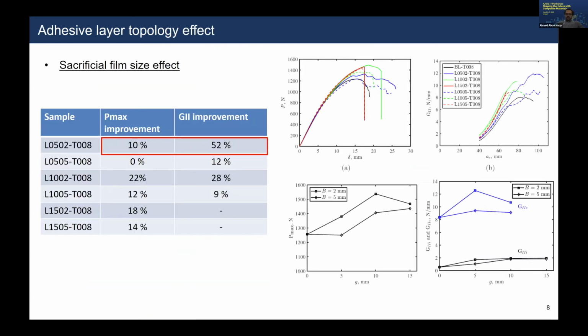For the topology effect, we study different P and G values for this bio-inspired adhesive joint. We reach the conclusion that the smallest crack width and the smallest G achieve a good improvement in fracture toughness and maximum load as well. The maximum load differs with the change of P and G, but finally we get a conclusion about the maximum toughness improvement for this joint.